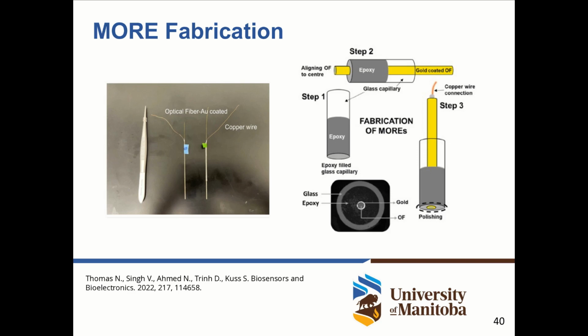of biological samples. The fabrication procedure is shown here on the right. It starts with a glass capillary in step 1 that is filled with epoxy. Then we use an optical fiber that is gold-coated and push it through this partially cured epoxy. Once it's fully cured, we can polish the tip in step 3 and connect the copper wire to assemble a micro-optical ring electrode that resembles very much the dimensions and features of a regular ultra-micro electrode that we have been using in the past.